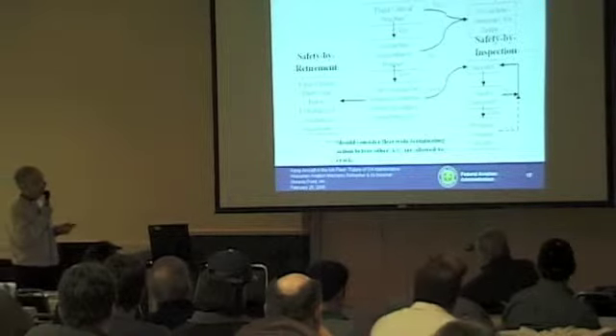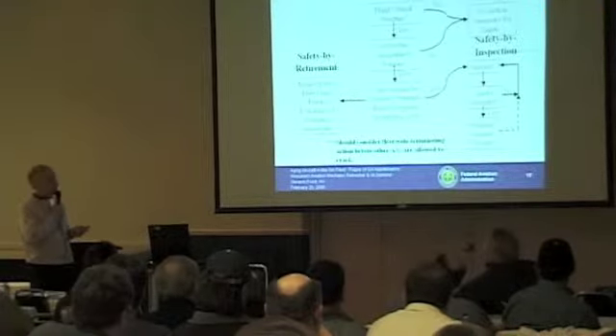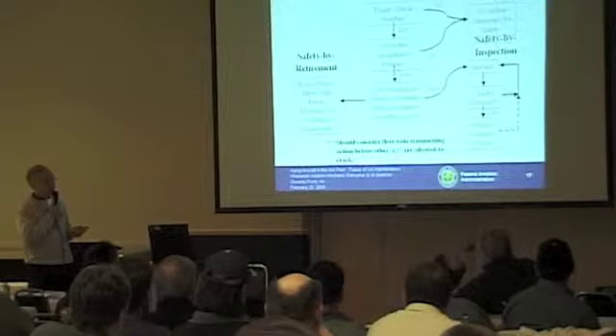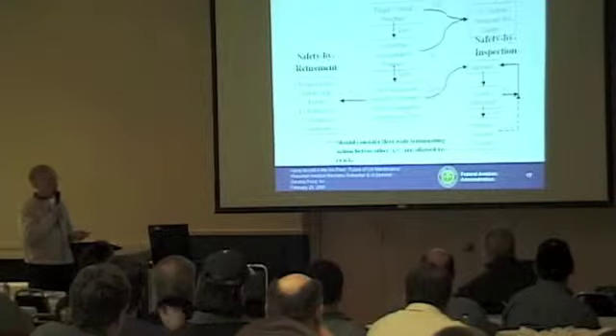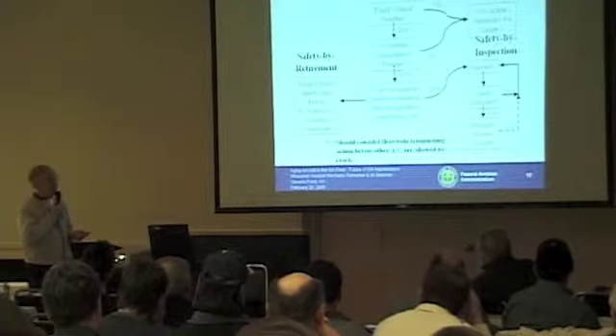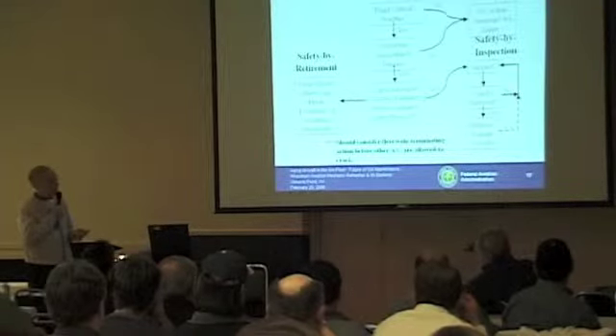So if it's susceptible to fatigue, can I find the crack before I lose that required limit strength? If I can find it, then I can go over here and I can inspect for it. Do I find a crack? No, then I inspect it. The T6 is sitting right here. We've got a 200-hour repetitive inspection on those angles. Every 200 hours we're going to be looking for those cracks. And as long as they stay in this little loop, everything's okay. If we find a crack, we can replace, repair, modify. In the case of T6, that would be new angles. But maybe there's a repair that can be done for a particular airplane, that sort of thing. And then we go back in and we stay in this inspection mode for that new part.